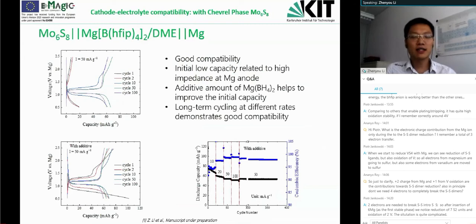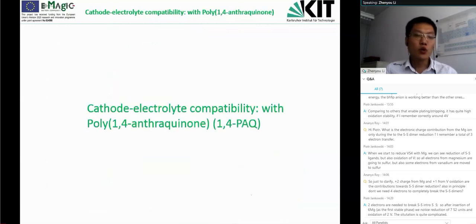Also, in the long-term cycling at different current rates, we see that the cell could be cycled for more than 300 cycles. And this also means that a trace amount of this magnesium borohydride will not affect the long-term cycling. And this is also something I want to mention. So with this successful compatibility test, we also tried another cathode which has a higher capacity and also a higher voltage. So here I want to present this polymer cathode, the polyanthraquinone structure.